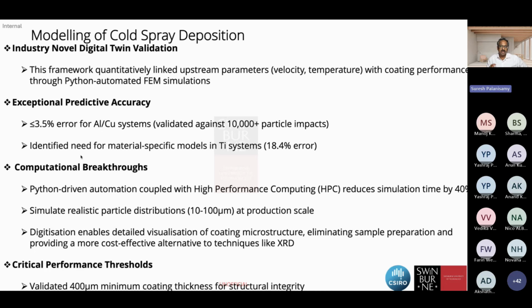However, the challenge is that most of the modeling work being done focused on up to the nozzle end, where the gas particle is propelled, how fast it is coming, and what kind of temperature is achieved for different material types. So quite a lot of work is focused on the nozzle. But when you come to the deposition, because it's challenging to get a multi-layer deposition, extensive work needs to be carried out. Even achieving 10,000 particles will take days and days of computing power. So even the work we did, we performed on a high performance computer, like a supercomputer, and even with that it takes quite a bit of time. However, it reduces the time significantly, by 40% compared to normal computation. So it needs extensive computing.